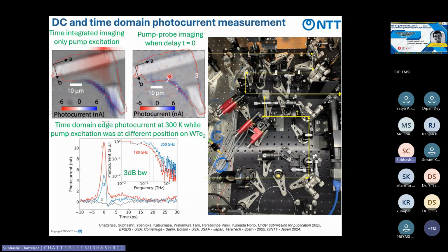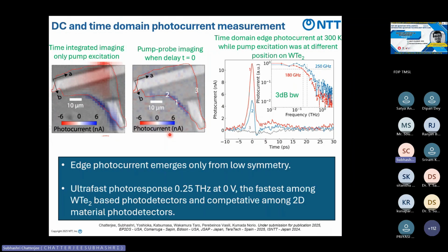But if we shine the light on the higher symmetry axes, like the A axis or B axis, we don't see any photocurrent signal. So we are confirmed that this ultra fast photocurrent is happening in WTe2, and it's a very very fast response, about 0.25 terahertz at zero voltage, which is competitive among other 2D materials.